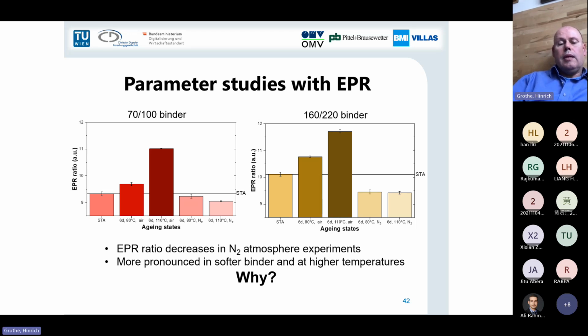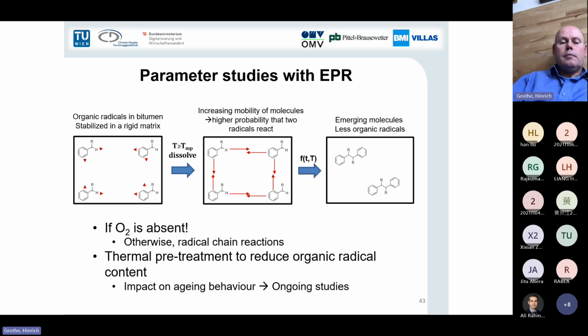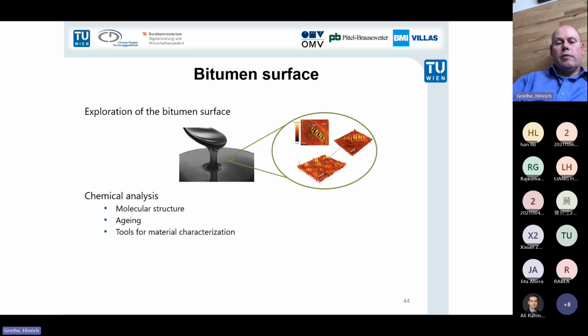And yeah, we see that temperature has an impact, because of the diffusion of the different molecules inside the material, and with higher temperature, it's easier to overcome reaction barriers, of course. And here is just an example. These are organic radicals, and these organic radicals, they can meet and they can form a new bond. And so it's a dimerization. This is typical in the absence of oxygen, and can be observed with spectroscopy. Okay, this is the chemistry.